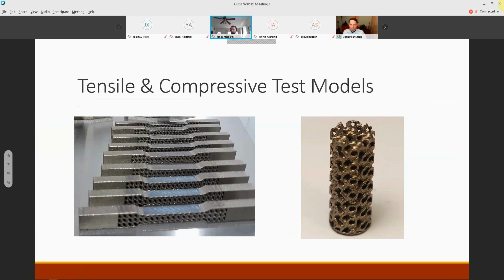Thank you. Shown in both figures is our printed specimen that we printed to perform our mechanical testing on. The left sample is the dog bone shaped specimen with the lattice structure that we printed for tensile testing. And the right sample is the cylinder shaped specimen with lattice structure as well that we printed for our compression testing.